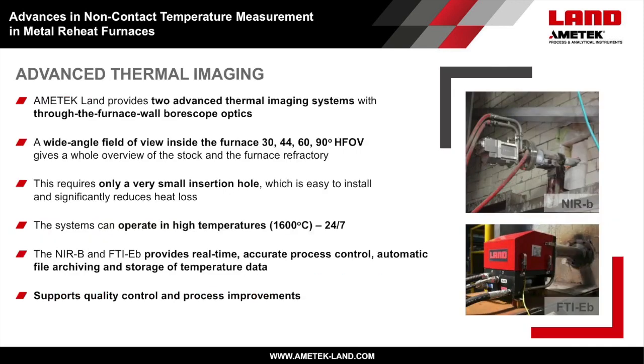Advanced thermal imaging systems provide much more details of the stock and the furnace temperatures, the temperature deviation, and additionally provide an online view into the reheat furnaces to the operators 24/7. With the NIR-B measuring at 1 micron and the FTI-EB measuring at 3.95 micron, two industry-proven systems are continuously working in many reheat furnace applications around the world. Different fields of view provide different wide-angle optics to get the optimum view and measurements related to the specific furnace and the camera position, working at measurement temperatures up to 1600 degrees or 2912 Fahrenheit.